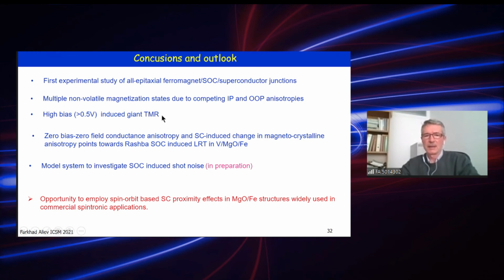These systems are important for application because they have very high bias tunnel magnetoresistance, and zero bias conductance anisotropy and superconductivity in exchange with magnetocrystalline anisotropy points towards the effect of Rashba spin-orbit coupling induced long-range penetration.